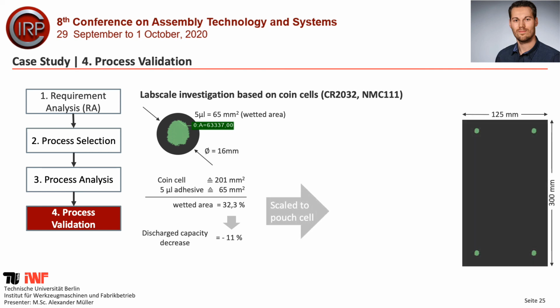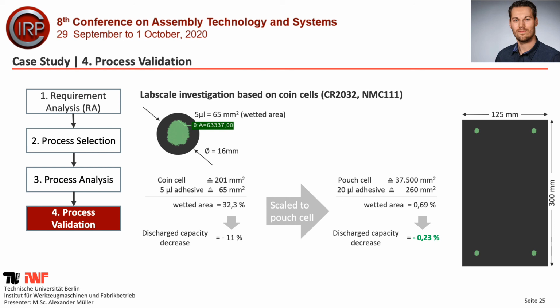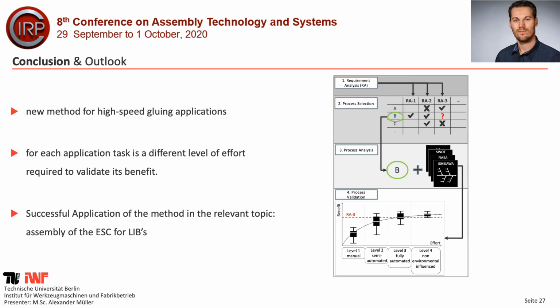But when you scale up to an automotive industry battery format, then you have a wetted area of less than 1%, and this means you have a discharge capacity loss, in a linear direction, of 0.23%, which is nearly nothing. So I have presented to you a new method for high-speed glue application. It depends really on your application case how much effort you have to put in to get your results. And we checked and proved that it will work for our really specific topic.